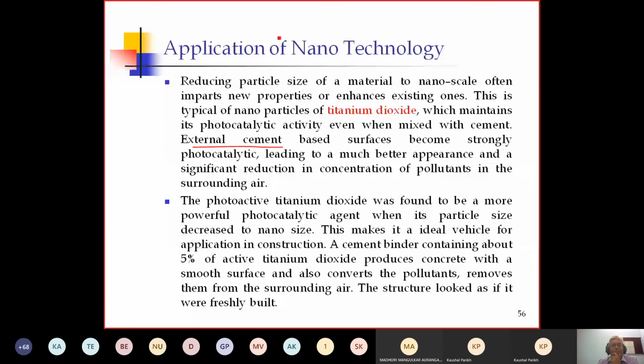Photoactive titanium dioxide was found to be a more powerful photocatalytic agent when its particle size decreased to nano size. This makes it an ideal vehicle for application in construction. Titanium dioxide is a powerful photocatalytic agent, right? A cement binder containing about 5% of active titanium dioxide produces concrete with a smooth surface and also converts the pollutants, removing them from the surrounding air, and structures look as if freshly built.